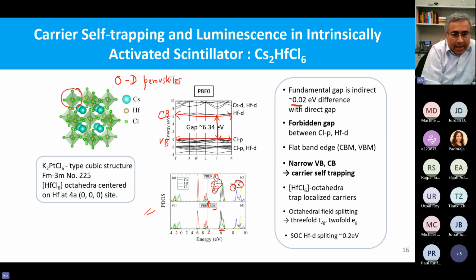Why do they act like that? Because of the octahedral crystal field. Go back to this. This is the octahedra, and this is the crystal field created. Under that crystal field, D levels are seen to split like so. The lower energy T2G levels create the bottom of the conduction band, and the higher energy EG levels are in the higher conduction bands. Those are the details, but it's important to notice them and check your calculations that indeed those are the cases.